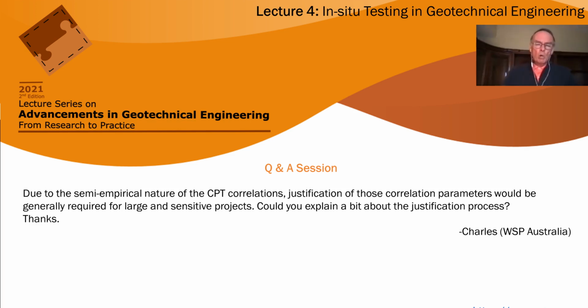And so the reason I proposed that chart was to say, look, if you have a material that has significant microstructure, you need to be aware that some of the empirical correlations may not work as well as they do in the ideal soils. Now, how badly they will be off depends on how much microstructure there is and what type of microstructure. So, for example, if it's identifying significant microstructure, that's where knowledge of the geology comes in. Because if you know that you're dealing with a very old deposit, so you're anticipating that you're dealing with maybe a